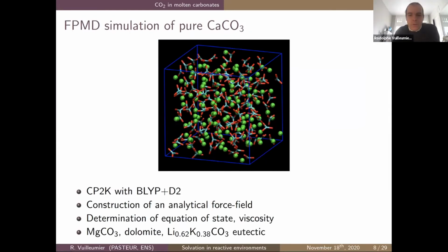So we started, and we'll go very short on this, on the simulation of these pure molten carbonates with first principle molecular dynamics. We were interested, for the geochemists but also for these applications, in the determination of the equation of state and transport properties like electric conductivity and viscosity for a bunch of systems, from the ones of interest to geologists, magnesium carbonate and calcium carbonate, to the ones of interest for these applications, which are more alkali carbonates: lithium, potassium, sodium carbonates.